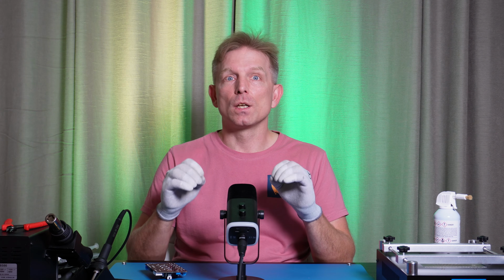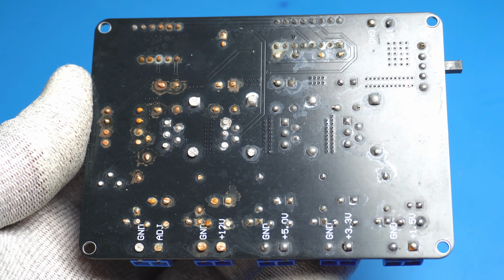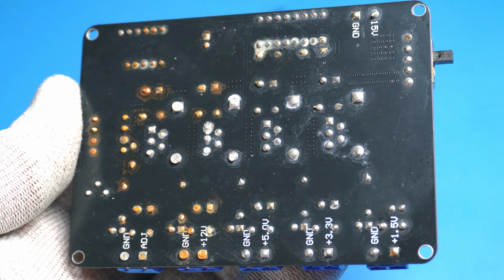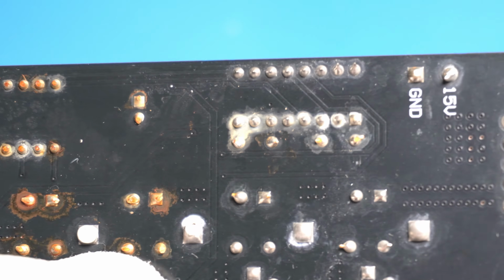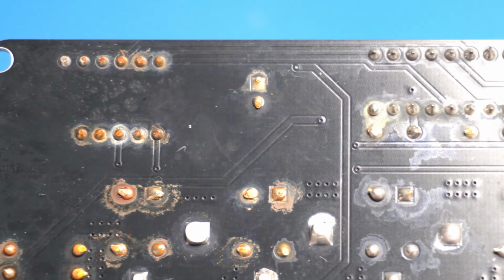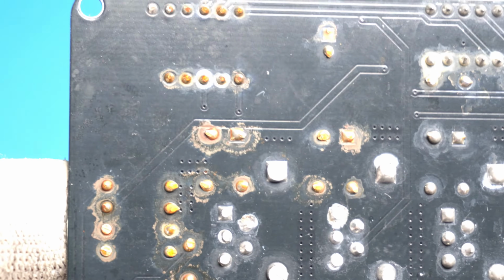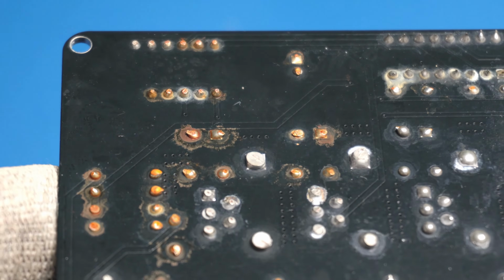Why am I showing this? Look what's happened. The part of DIP component leads that I additionally soldered remained clean and undamaged. Yes, there is an oxide film on the metal, but there is no corrosion. Now look at the DIP component joints that were simply cut off. The cut and exposed leads of DIP components have become corroded.